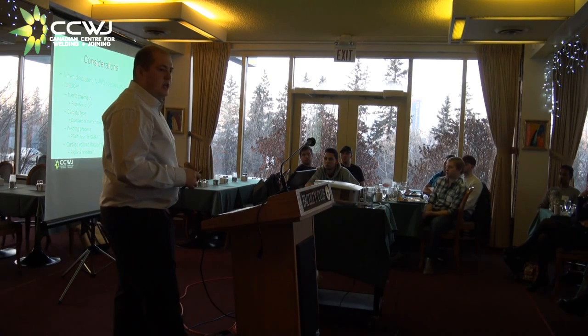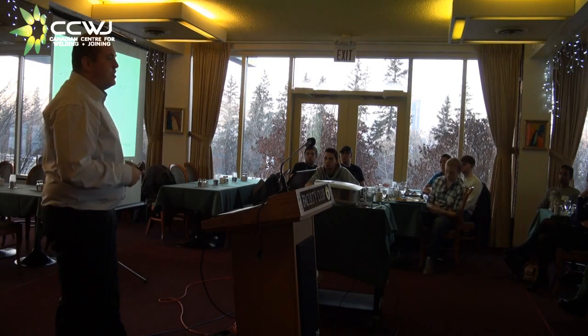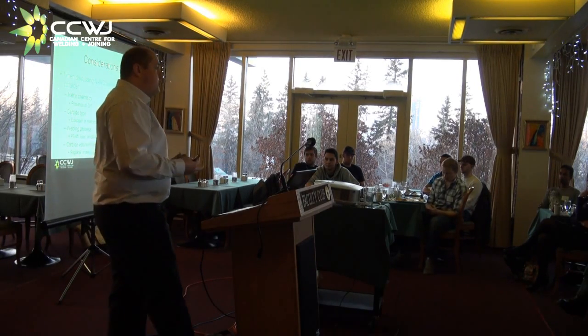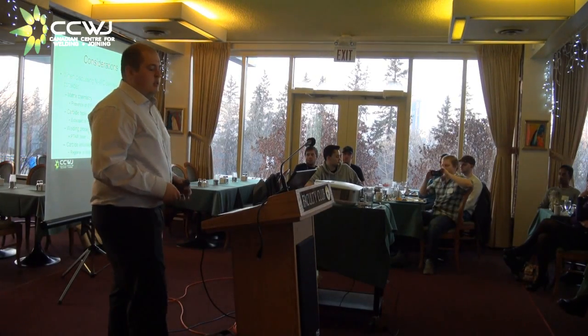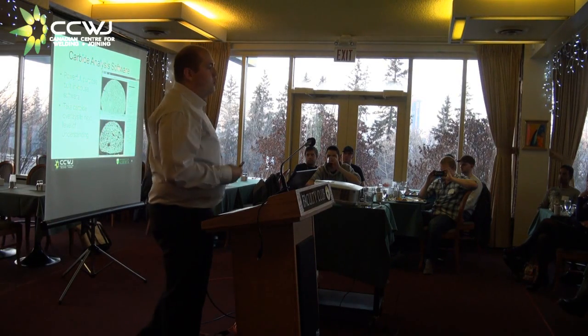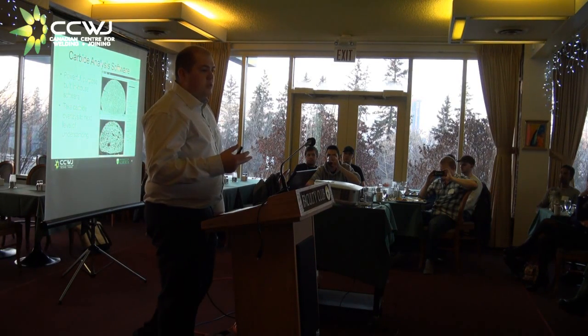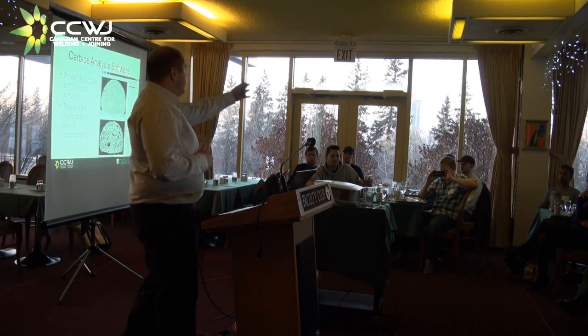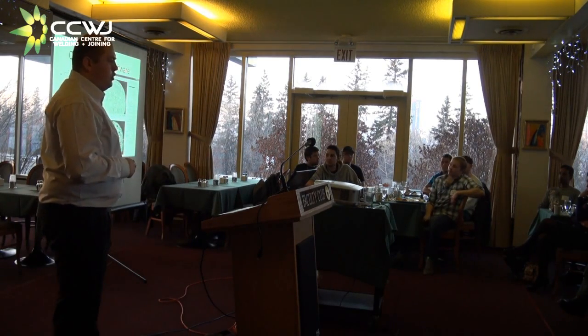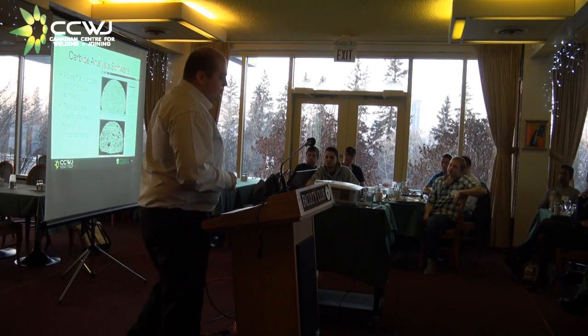Also, how was the carbide volume fraction measured? There are two ways to do it. There's a regional analysis, so a high magnification microscope image of a small region of the weld, or there's an overall measurement. Now, the overall measurement is going to be more representative of the wear performance in service. And this is where Matt Dewar, who's sitting right here today, comes in. We told him about the problem, and over the weekend he got into it and built a computer program for us to measure these carbides.